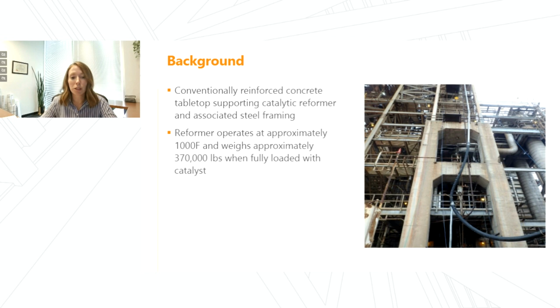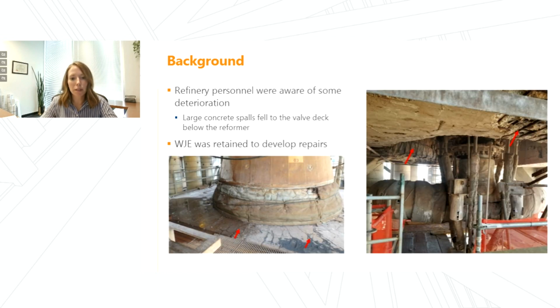Now, the reformer, I'm sure you're all aware, operates at a high temperature, approximately 1,000 degrees Fahrenheit, and it offers a significant load to the structure of 370,000 pounds when it's fully loaded with catalyst. So this is a substantive load at a high temperature on a reinforced concrete element. The refinery personnel were aware of some deterioration, as you can see here in the photos. The red arrows point to some spalls, some large cracks that we saw. And this really elevated the structure's risk profile. But the real increase started when a large concrete spall fell to the valve deck below the reformer.